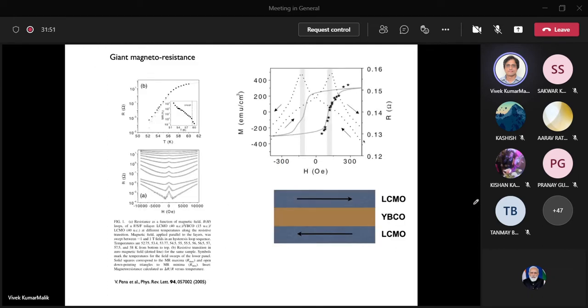There are different kinds of phenomena which could be observed in this system. What we can observe is a large magnetoresistance, a kind of giant magnetoresistance, only when it goes into the superconducting state. This is observed in a tri-layer, not a multi-layer, where you start with LCMO, YBCO, and LCMO. When the magnetizations of both LCMO layers are anti-parallel to each other, then you see a large magnetoresistance. In figure 1a, you can see that the magnetoresistance around zero field keeps increasing and goes away when it is in the normal state. But this occurs only when it's close to the transition temperature.